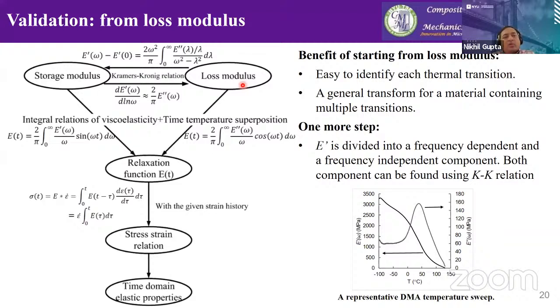When we are playing with the storage modulus and loss modulus, what we can do is we can apply another method where we can first estimate a frequency dependent and frequency independent component of modulus. The frequency independent component can just stay like that, and the frequency dependent component can be converted into the time dependent information, and then we can add it up back to recover the elastic modulus. So equations are simple here. You can see instead of sine, we got the cosine at this time. If you are starting with the loss modulus, you can go back to the same scheme of equations and find the elastic modulus. So this Kramers-Kronig relationship is important in this case because it defines the direct relation between storage and loss modulus quantities.